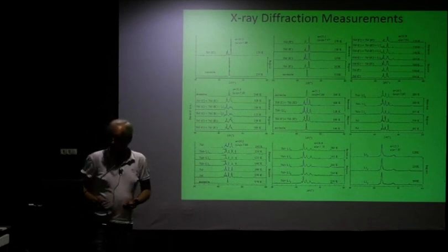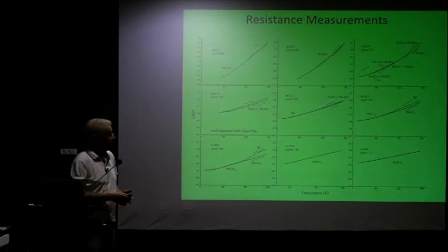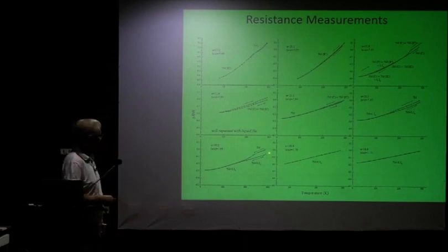So when you go back and look at the resistance data, for example, it's all iterative. Then you say, so what I see from my X-rays is, for example, for this sample, I am in the 7M structure. That's what it says. And then I go down in the temperature, and I come to a point where the X-ray data taken down here tells me that I have a 7M plus L10.